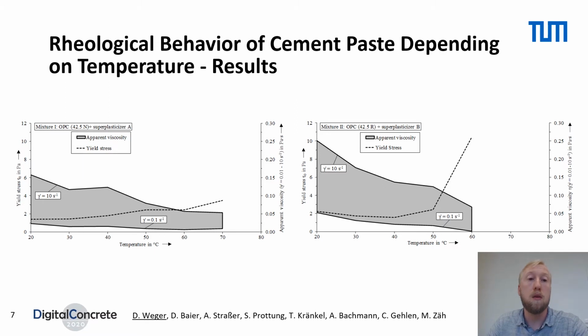For evaluation of these results, it's good to know that the yield stress of the cement paste should be smaller than 3 to 6 Pascal to achieve sufficient penetration behavior. But this value depends on the grain size of the particle bed.